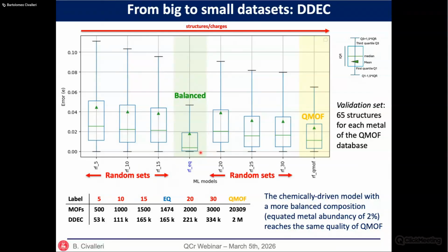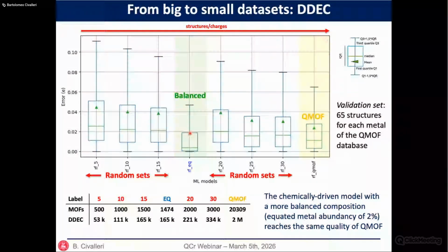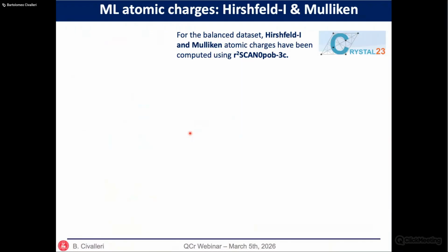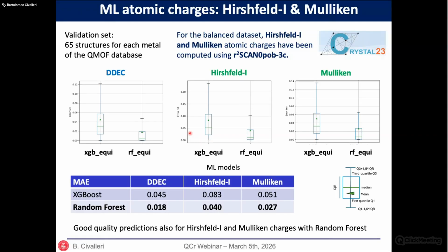So this means that selecting this data set properly allows us to reach the same accuracy in the prediction of the DDEC charges. By using this data set, we extend the calculation to Hirschfeld and Mulliken charges using our composite method as implemented in a development version of the Crystal code. And we get, again, nice results in comparing these for this validation set of structures, reaching an accuracy that is reasonable for the prediction of charges.